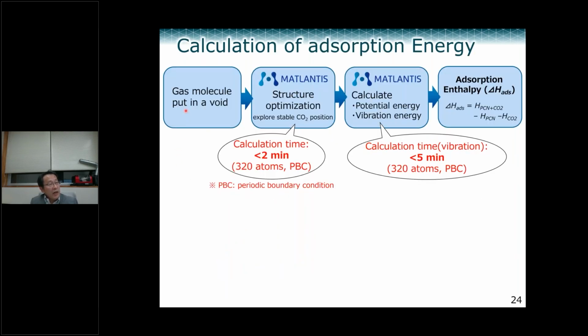So first, we made a model using CO₂. We put CO₂ in a void in the X-ray structure. Then we optimized the structure. In this case, surprisingly, the calculation time is less than 2 minutes. If you calculate this one using DFT on a workstation, I think we would spend more than 1 week.